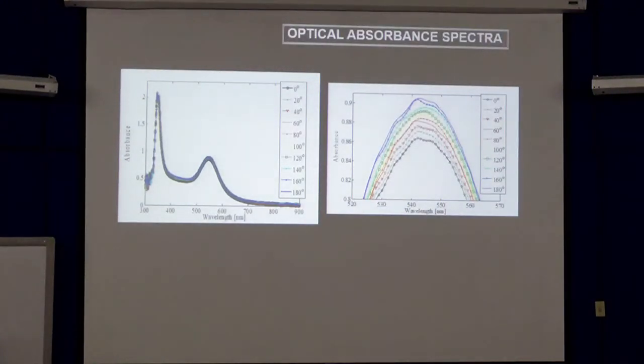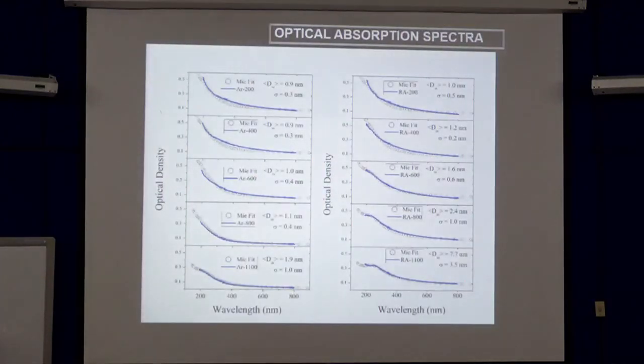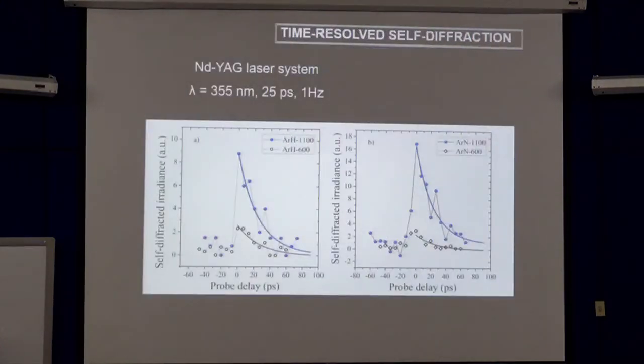This is a demonstration of the plasmonic response of the sample. If you have the modulation of the position in the testing, you can see that a change in the absorbance is going to be obtained from the modification of the position of the bimetallic sample. So these are some spectra of the platinum in order to see that the plasmonic response does not appear when you have small nanoparticles, but there is a size that allows you to obtain the plasmonic response and the ultrafast response of the platinum.